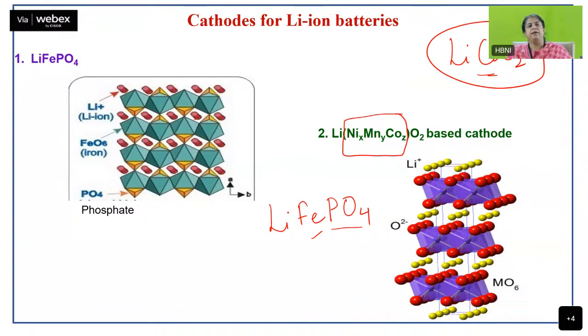And these lithium ions, when I am charging your material, will move out of this electrode, go into the electrolyte, and go to your anode, which is carbon. Okay. Now it is charged. Once you discharge it, this lithium ion will come back from your carbon through the electrolyte to this particular cathode, which in the present day is lithium cobaltate, but there are futuristic materials like LiFePO4 and NMC electrodes.